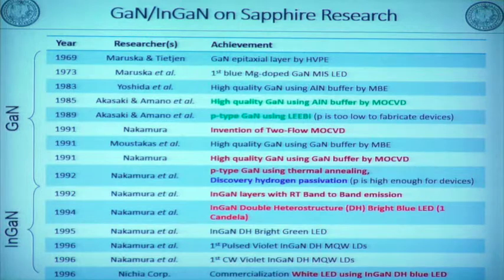Also, this shows the history of gallium nitride growth and indium gallium nitride based devices. You can see that in '85, Professor Akasaki and Amano invented the aluminum nitride buffer layer to improve the crystal quality. In '89, they invented P-type gallium nitride using low energy electron beam irradiation treatment. That's why they got the Nobel Prize, because they obtained the first P-type gallium nitride. In my case, I started gallium nitride growth in '91.